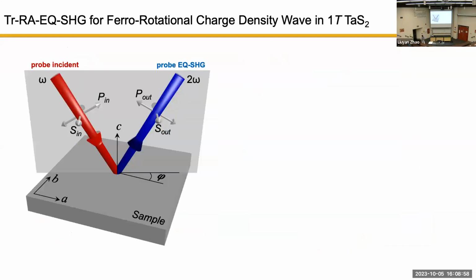Once we can see the domain distribution, one experiment we can now do is the dynamics. If we have both domains when we do dynamics, it's a bit confusing. If we can zoom in to one domain to do the dynamics, things could be cleaner. To do the dynamics, we still use the very same detection procedure, but on top of that, we introduce a so-called pump laser. Basically, we give a blast of laser excitation onto the material, and following that I do the flower pattern measurement. Then I can tune the time difference between the excitation and my measurement.